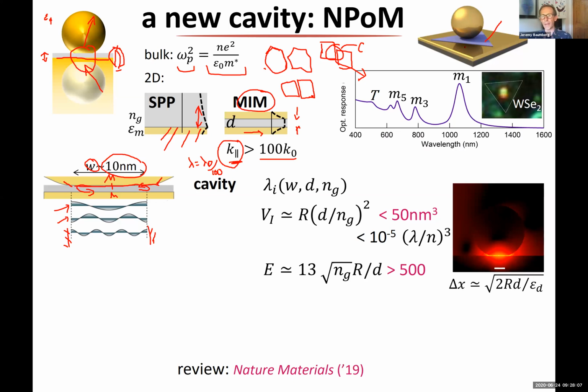What's nice about the nanoparticle on mirror is that you don't care because it's essentially flat. And say you bring your cube down here, it's perfect, right? You just have to make a nice intermediate layer here. There are many more subtleties that we're finding about the shapes of the nanoparticles as well. But essentially, the nice thing is that it's very robust. As long as you can control the facet size at the bottom, which you can even control optically, then you can control precisely everything about this geometry.